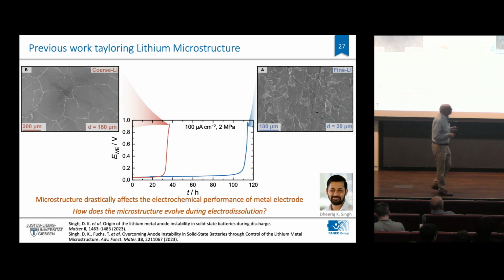Now, a postdoc in my lab had started earlier looking into that, and he already made electrochemical experiments and showed nicely that if you have a coarse-grained lithium and a fine-grained lithium, the electrochemical properties are indeed quite different. The fine-grained lithium, you see here much smaller grains than here, delivers much more charge for a longer time with the same current density, so more charge than the large-grained lithium. So the grain size microstructure has an influence.